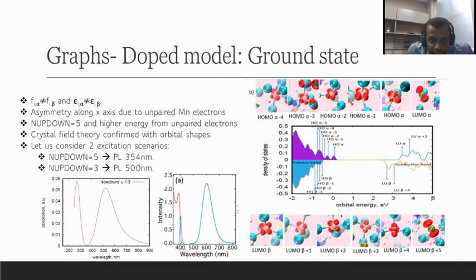So for the doped model at the ground state, like we said before, we're not going to see any symmetry. The occupation for alpha is different than for beta, and the energies for alpha are different than for beta. We can see two extra mountains in the alpha part that are absent in the beta, and those are the 5 extra electrons in the alpha orbitals contributed from the manganese.